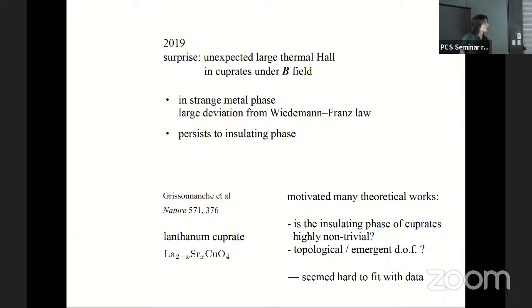Just maybe you can remind, the Wiedemann-Franz law is a relation between the usual electrical conductivity and thermal conductivity. Right, it should be proportional. In the usual case, it's proportional to temperature. Right. So they found a large deviation from that. At the beginning, they thought maybe the strange metal is just very different from the usual electric transport. But later, they found even in the insulating case, where there's no strange metal electrical degree of freedom anymore, there is still a very large thermal Hall effect.